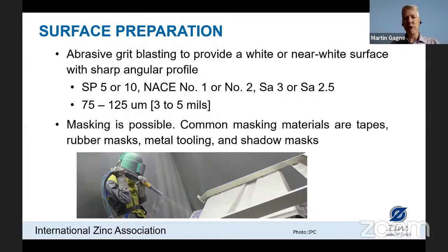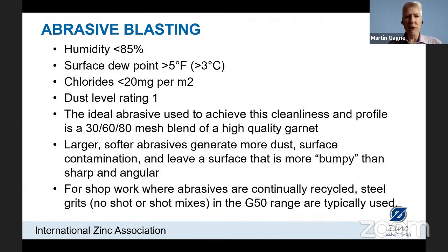If there are areas that we do not want to be blasted, masking is possible and common. We can put tapes or rubber masks on an area of the steel structure that we're blasting so that the surface is not roughened. But generally, anywhere we are going to coat with thermal spray zinc, we want to have this sharp angular profile and a clean surface. So conditions for blasting, just like paint, we have humidity and dew point considerations, a little bit more forgiving than for paint. We can have humidity up to 85%, surface dew point greater than 3 degrees Celsius.